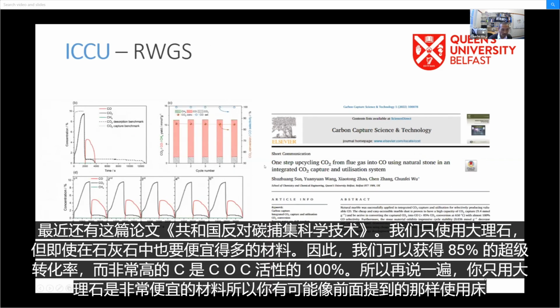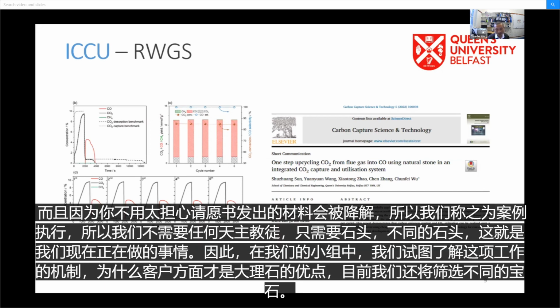Recently, we published another paper in Carbon Capture Science and Technology. We only use marble stone, a much cheaper material even than limestone. It can get 85% CO2 conversion and 100% CO selectivity. Again, you just use marble stone, a very cheap material, so potentially you can use a fluidized bed as previously mentioned, because you don't worry too much about material degradation and attrition issues. We call it a simplification: we don't need any catalyst, just different stones. That's what we are doing now.